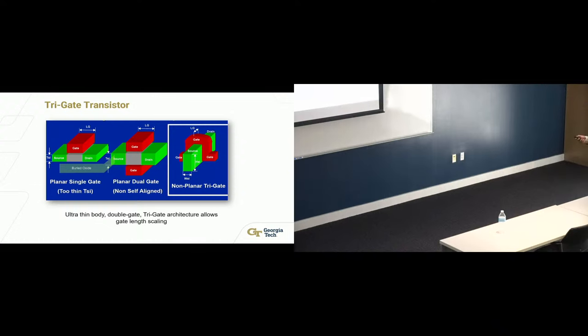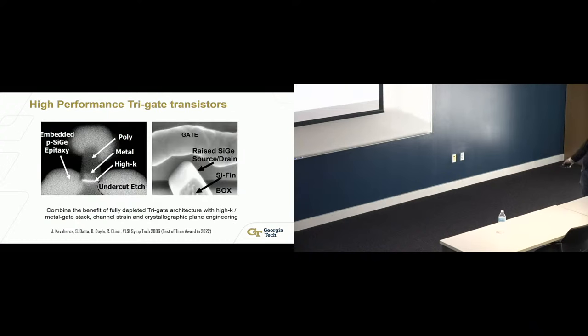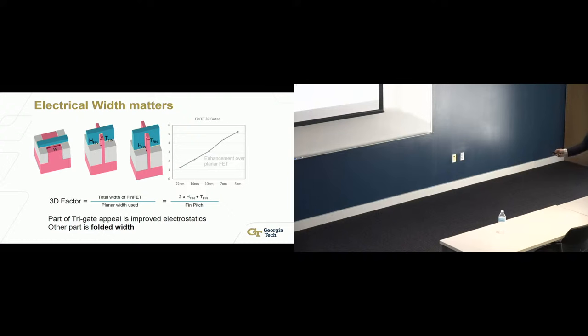But the big issue at that point was that now you're going to make transistors not on a beautiful, nice silicon surface. You're going to actually etch out these fins, and you have to control the orientation of these fins, the right crystal planes, and make sure your transport is strong enough. The other question was how do we integrate the high-k metal gate stack? Nobody knew at that time how to do that. How to engineer the work function and target the threshold voltages. How do you do channel strain? Because it's one thing to do strain engineering on a planar surface, but how do you do that on a vertical fin? So that was one challenge. You don't want to give that up.